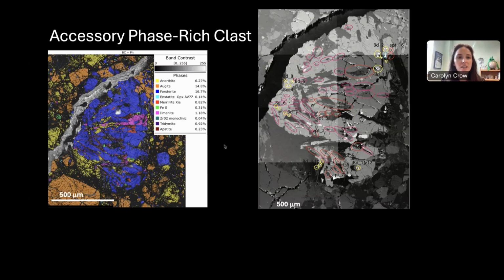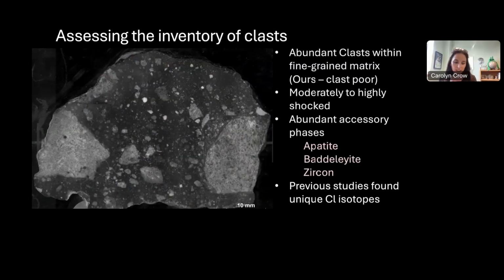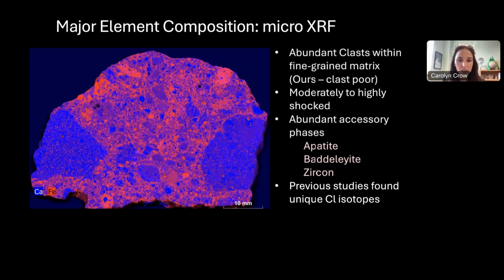And this is not necessarily the only interesting clast. There's another interesting clast in the second slab that we bought. Here's a picture of the second slab of the meteorite that we bought. You can see there's some really beautiful big clasts. But we took this sample and we did micro XRF mapping. So you can see that there's a various range of compositions of clasts within this sample.